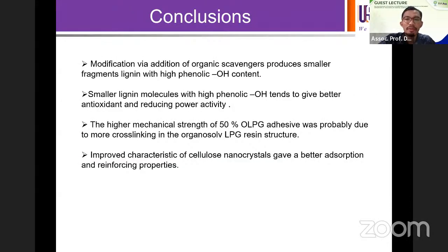So as a conclusion, what I want to conclude in my sharing today is that we can see the application of oil palm biomass waste for many applications. What I have shown to you is probably on corrosion inhibitors, adhesive, filler in coatings, and also adsorbent. It can also be used for other types, for drug delivery, for flame retardants, for composites and so on. And the improved properties of the lignin, for example, are actually due to improved aromaticity after modification. And for cellulose, after we do the acid hydrolysis and obtain nano size cellulose, this can provide a better surface area, which can give better adsorption and other types of properties.